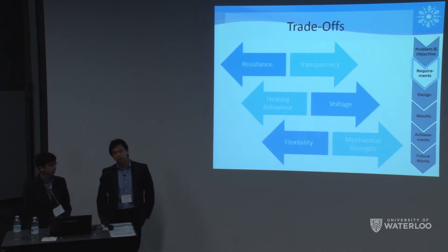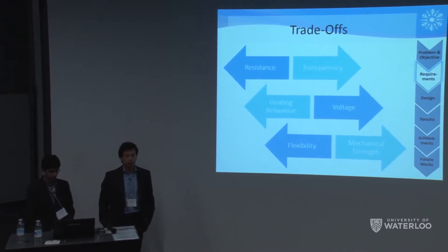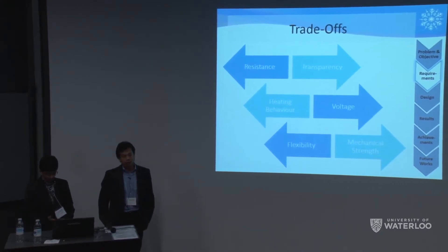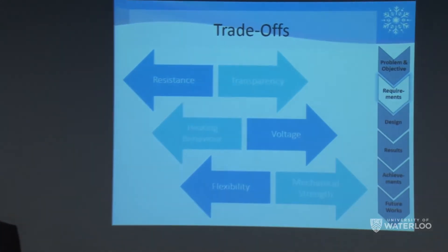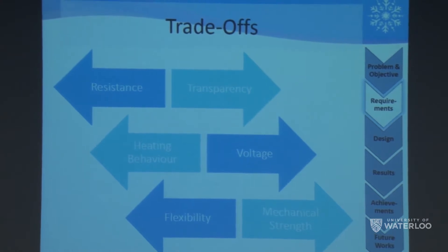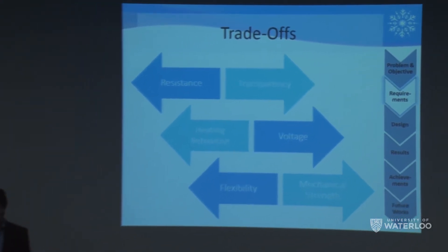From these criteria, we found several trade-offs. Being a thin film technology, it's easy to reduce resistance by adding more material loading. However, more material means less transparency — it will block light from passing through. Heating behavior is dependent on the voltage applied: more voltage means higher temperature and faster heating. Lastly, putting the film on a flexible substrate means bending might damage the film.